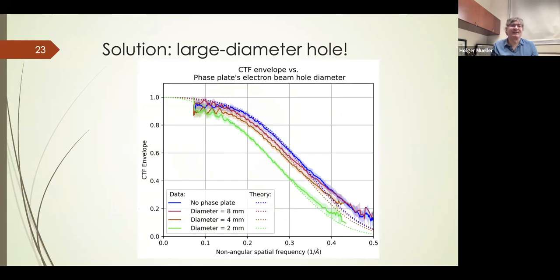The solution to that is easy on paper, but a lot of work in practice. We need to increase the diameter of the hole. So here you see measurement and theory for a 2 millimeter hole line up extremely well. And as the hole size is increased to 4 millimeter and 8, the performance of the laser phase plate installed is nearly indistinguishable from the performance of the microscope without the laser phase plate.